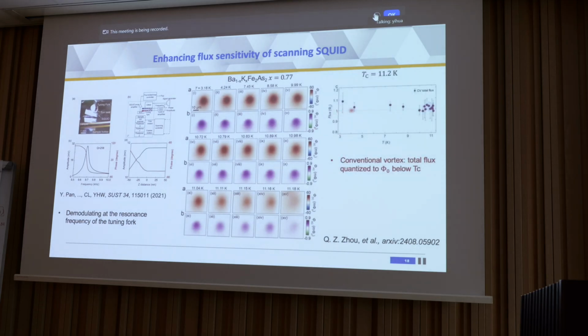And after doing the integration over the DC flux, we can see that indeed these conventional vortices do not change with temperature until Tc.